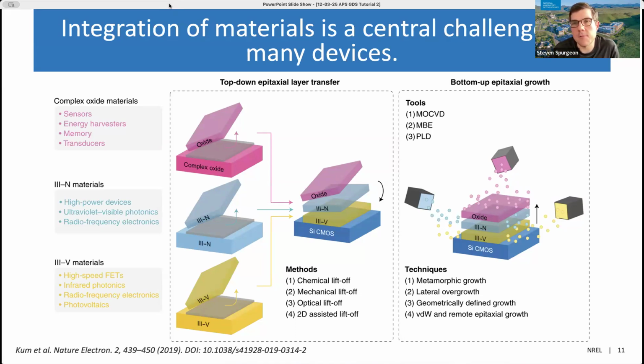Alternatively, the conventional approach is what's known as bottom-up epitaxial growth. These are things that the semiconductor industry has used for a very long time. But these are basically physical vapor deposition, chemical vapor deposition type techniques in which we use a single substrate. We control flux of atoms and different alloying elements and deposit them in a controlled manner onto that surface. And then we layer materials. Now, the challenge here is everything is constrained to the same underlying substrate. And so there's a variety of different defects that can form in these systems. Oftentimes, it's very challenging to stabilize many of these heterostructures.